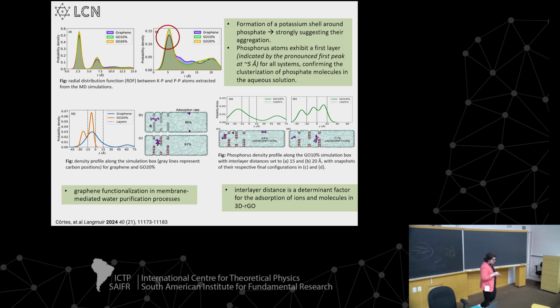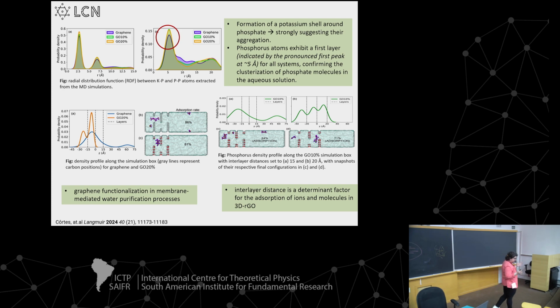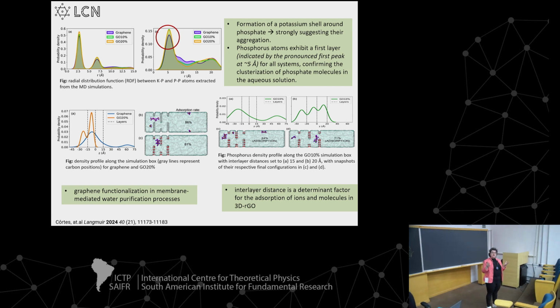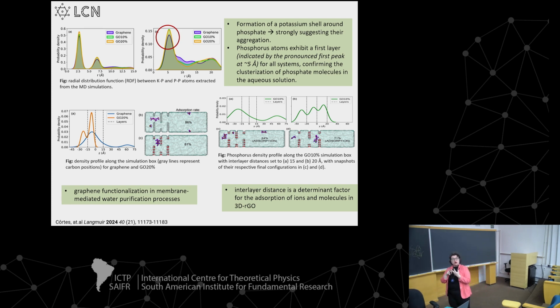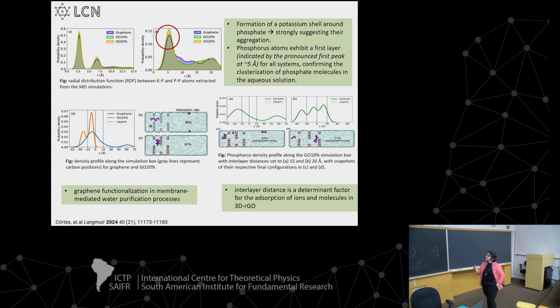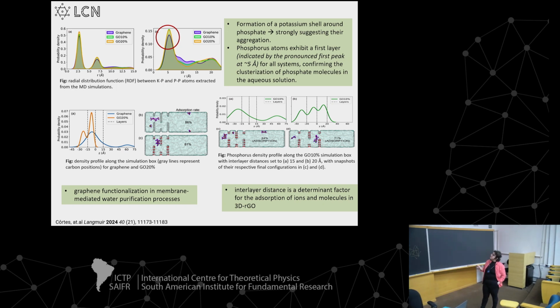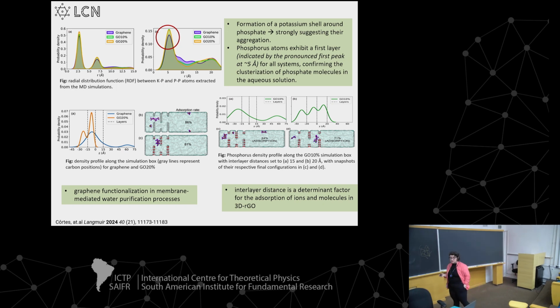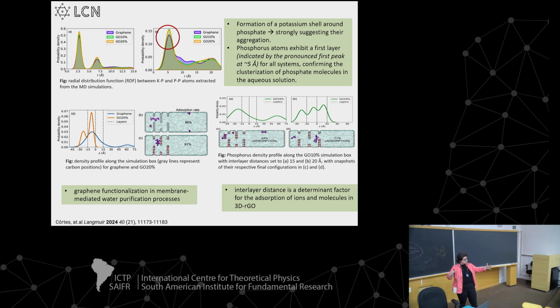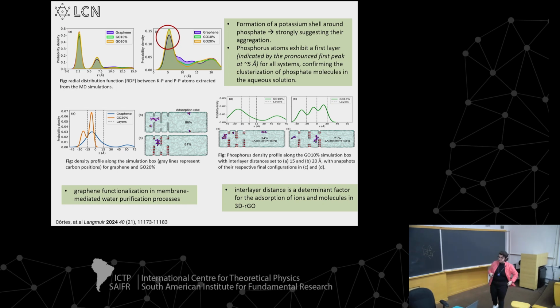This shows that it's not only dependent on the nature of the graphene materials, but also on the contaminant. So some contaminants aggregate, others not. So we need to combine the pore size, functionalization of the pore, and the nature of the contaminant. We also saw that the interlayer distance was a determinant factor for the adsorption of the ions and molecules. So the materials with more porosity and more functionalization are better to remove the phosphate.